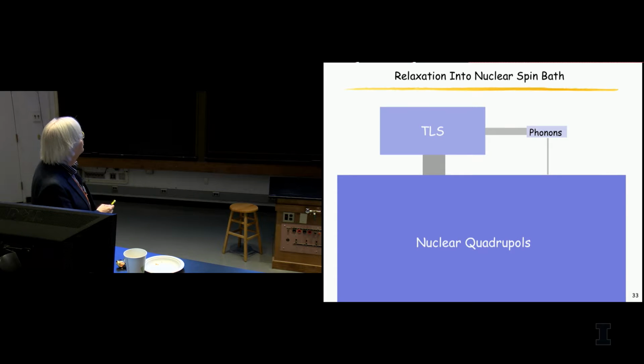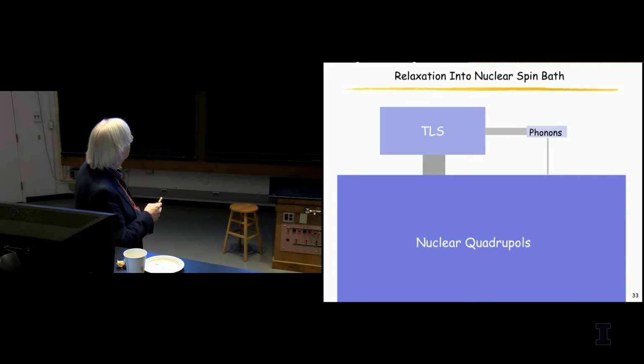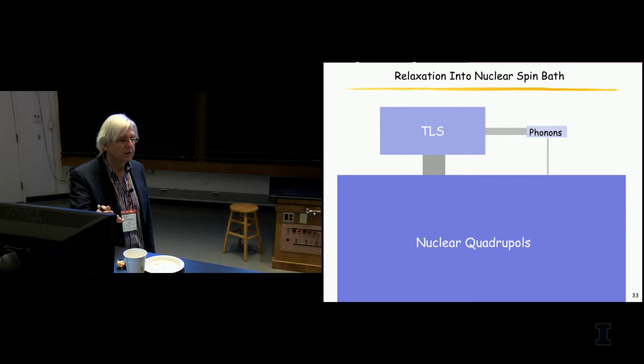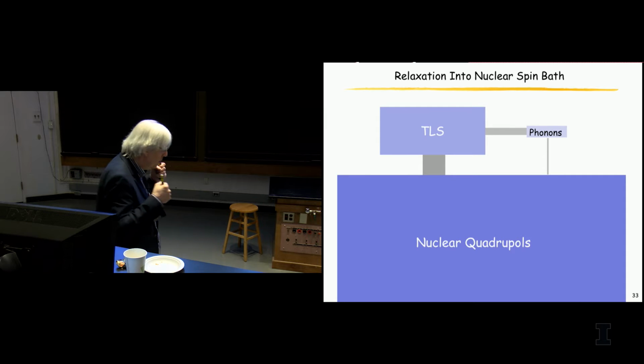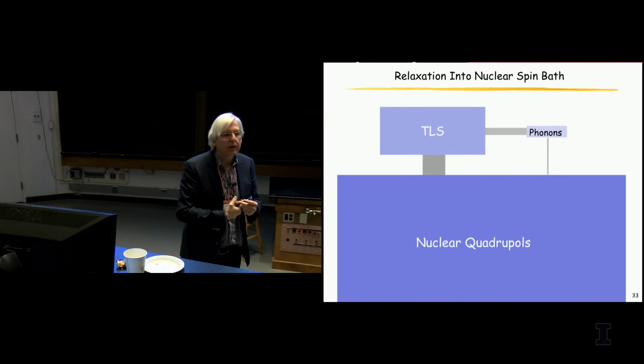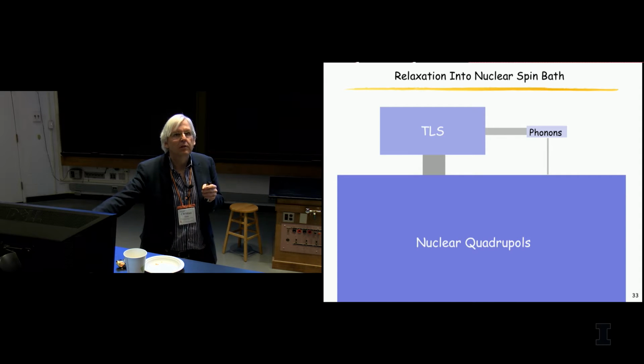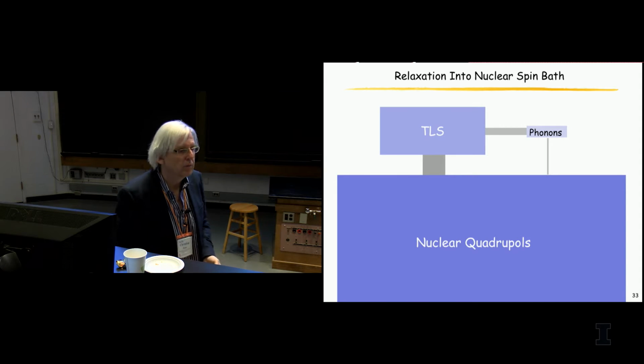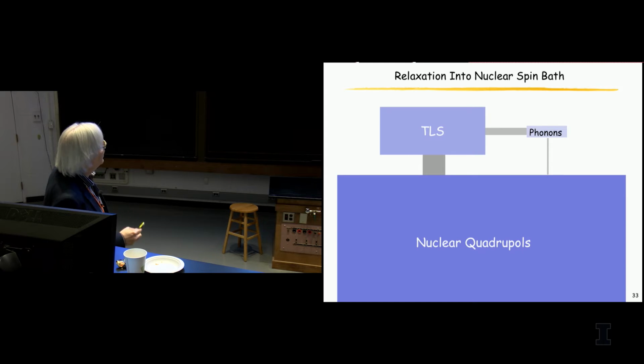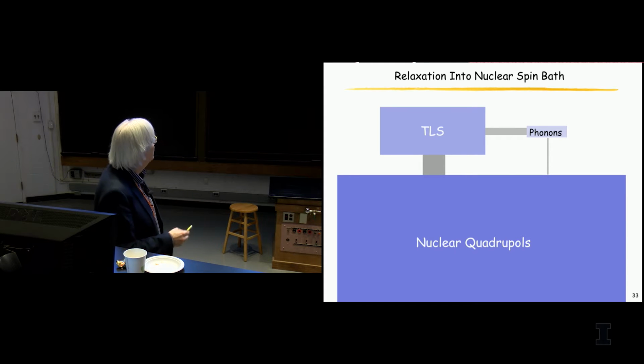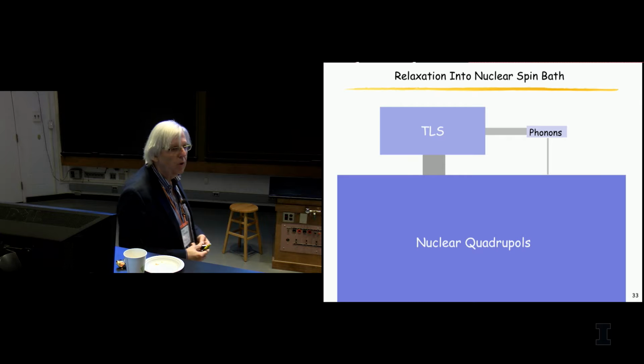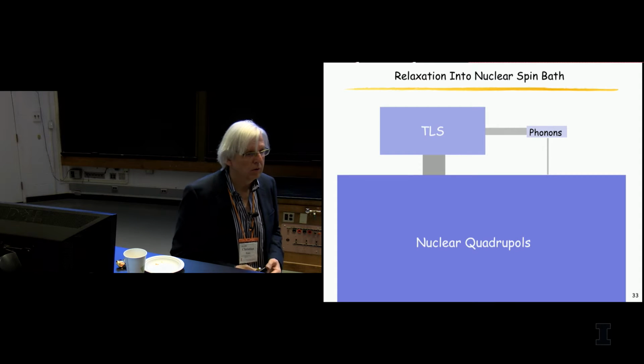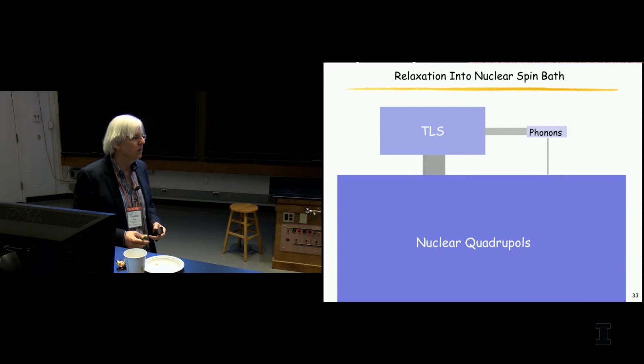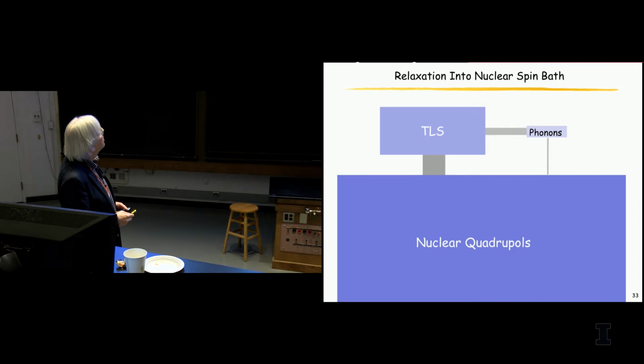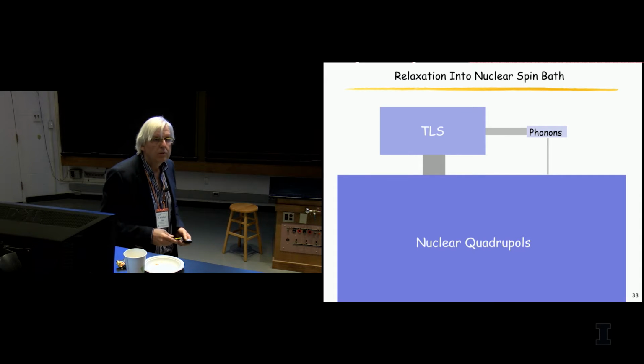Now, if you assume that there is some kind of coupling between those two, then energy could flow into the nuclear bath from the tunneling systems. Your electric field is shaking your tunneling system, and it relaxes into the nuclear bath. That's something which hasn't been considered so far. The nuclear bath may drain over time to the phonons, but the nuclei-phonon coupling is extremely weak at lowest temperatures. It's days or weeks or something like that. And of course, we have some coupling to the phonons. So how does this happen?